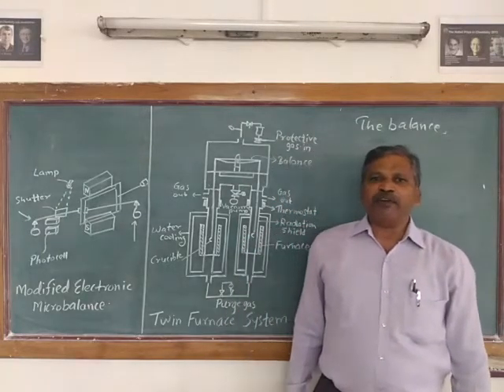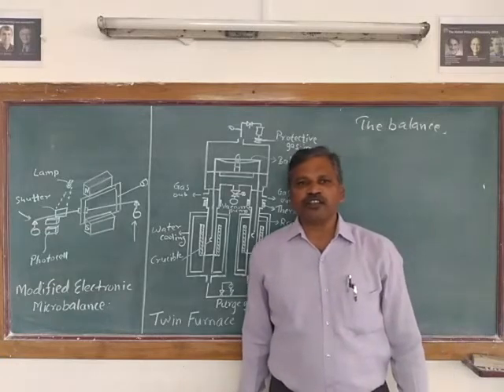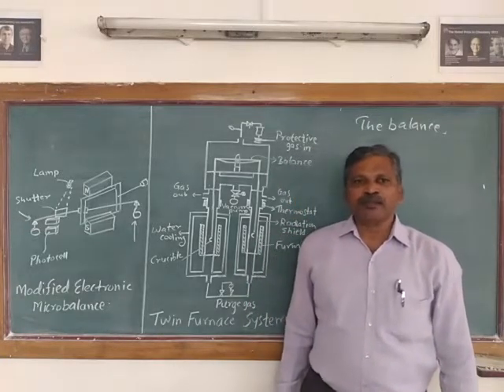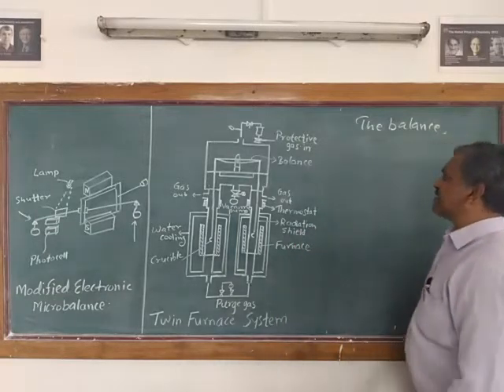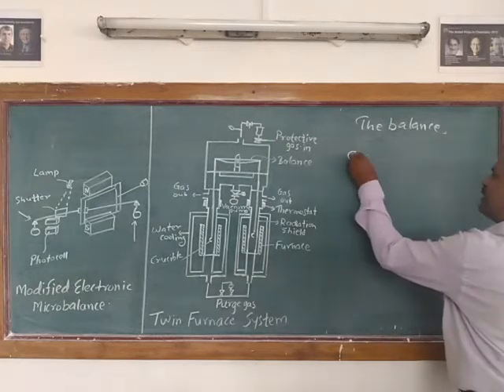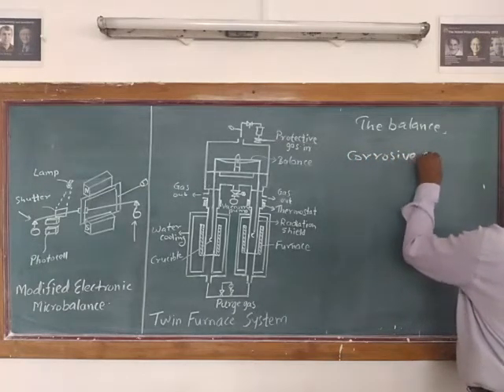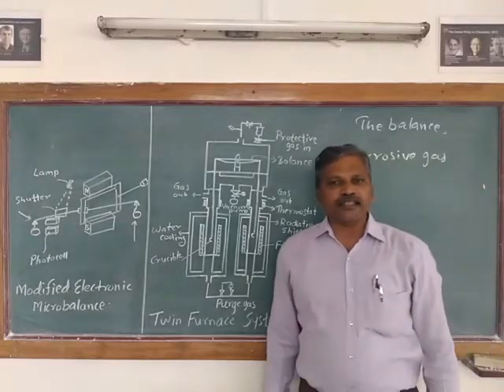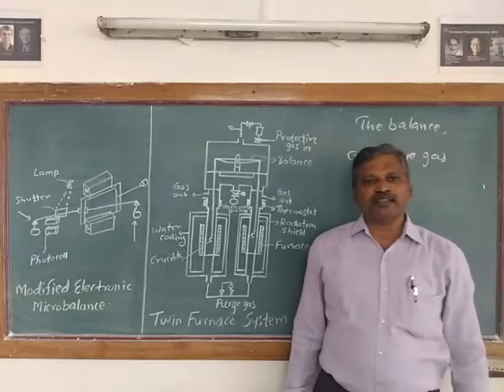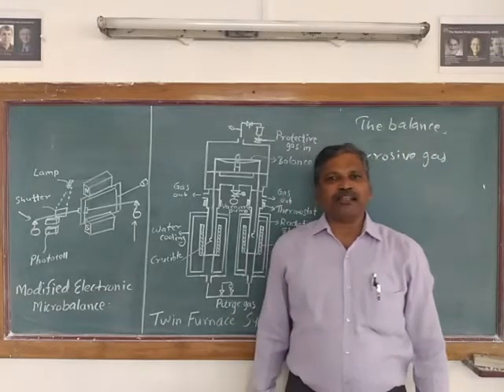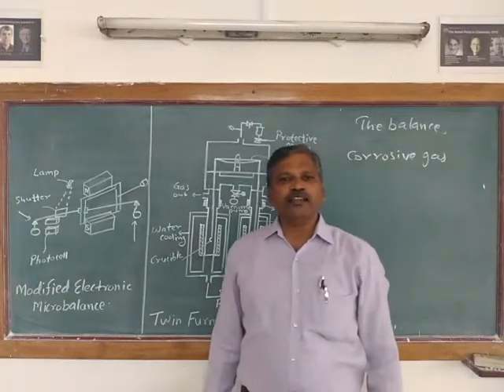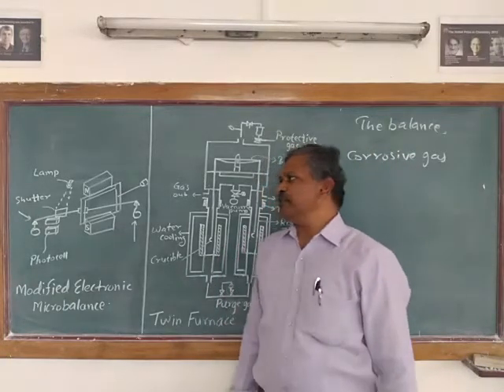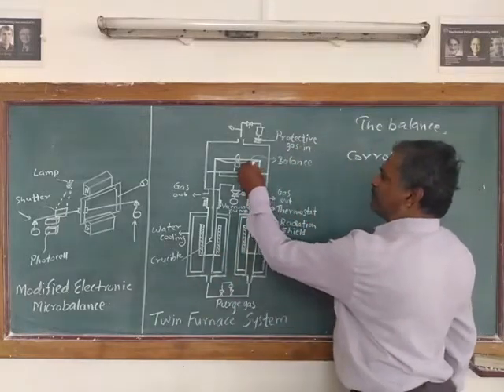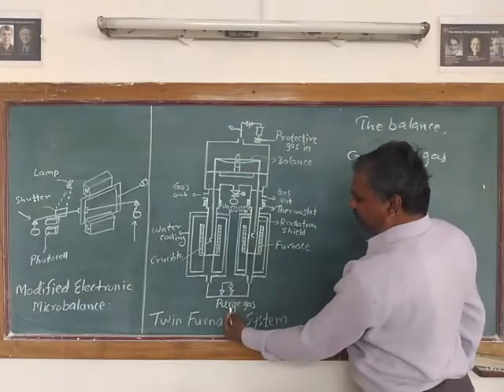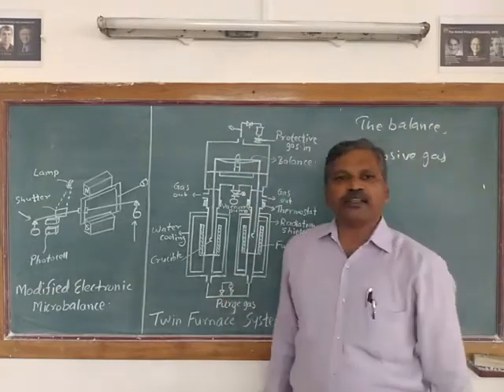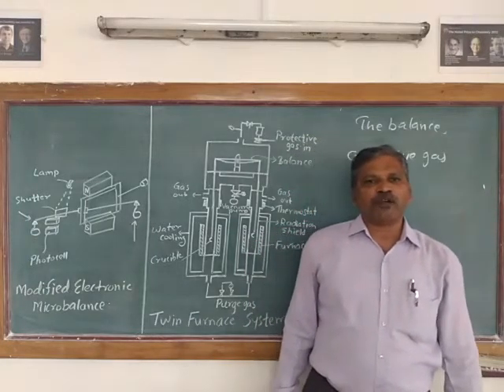The difficulties that may affect the operation of a balance used in conjunction with the furnace are most important. The presence of corrosive or oxidizing gases near the balance mechanism is most undesirable. The balance enclosure is often purged with an inert gas such as nitrogen at room temperature. In this diagram you can see the balance is purged with nitrogen gas. So the corrosive or oxidizing gases get removed around the balance.